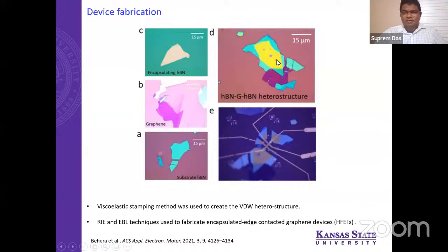Now you can see some of the bubbles inside. These are air pockets, air bubbles, but we have a technique to push them out, because we have to make sure that this interface is very connected and high quality. Otherwise, you will not get high quality transport and also noise. So after that, this is the final device. You can see the various leads, source and drain you can use, and it has a back gate where you can modulate the charge carriers.